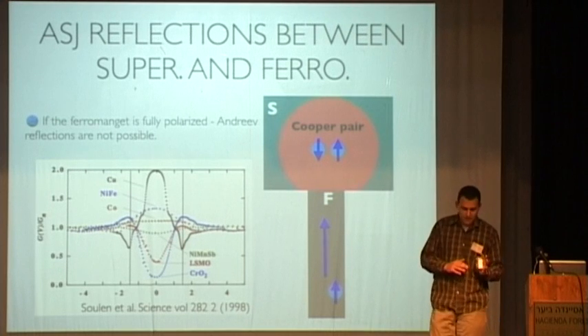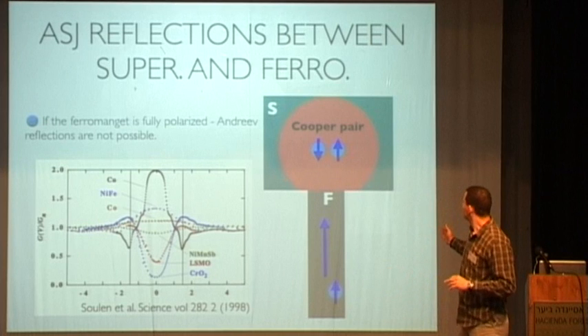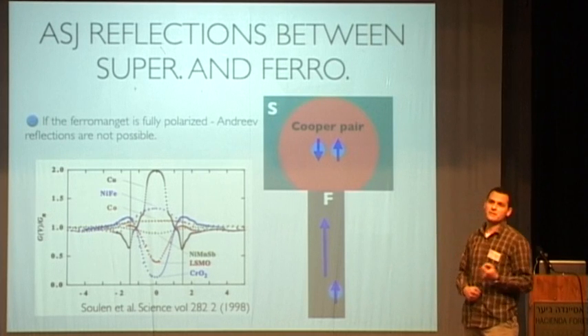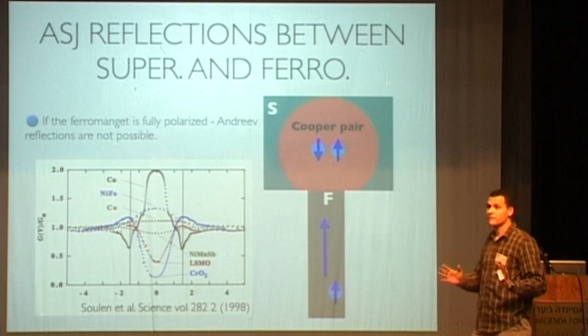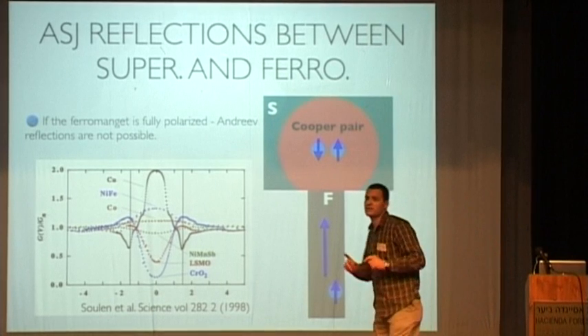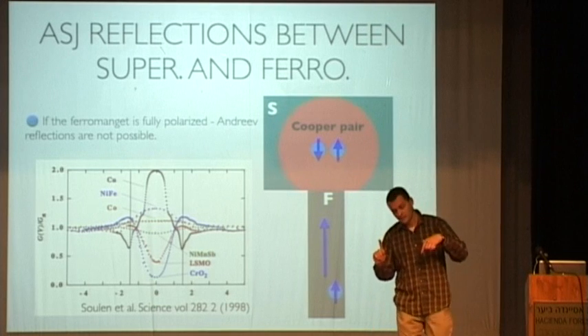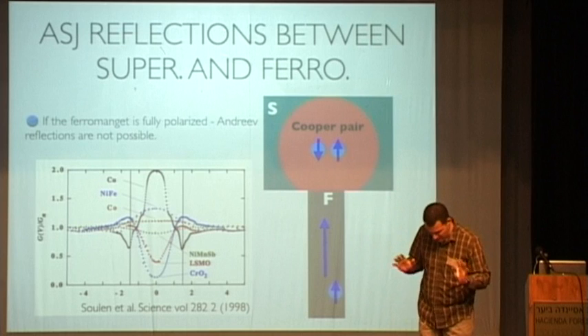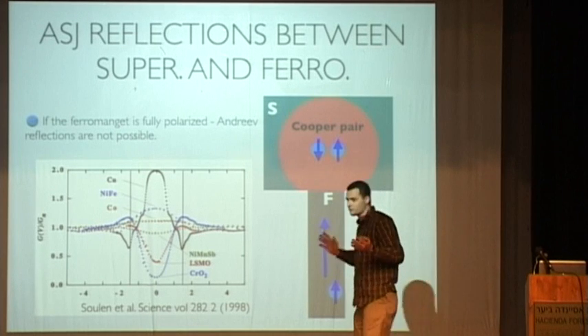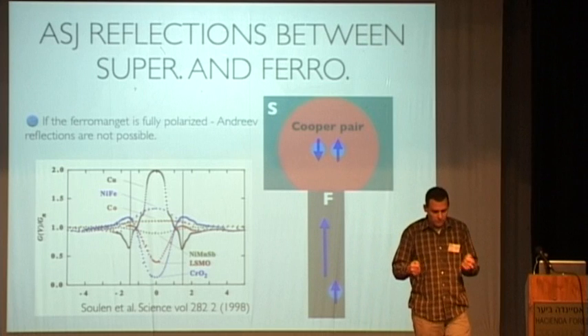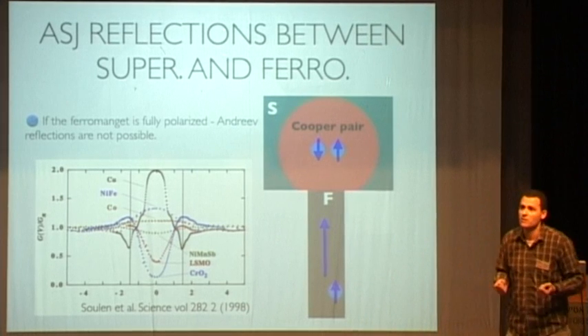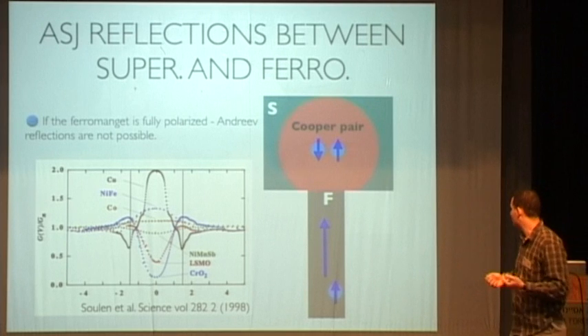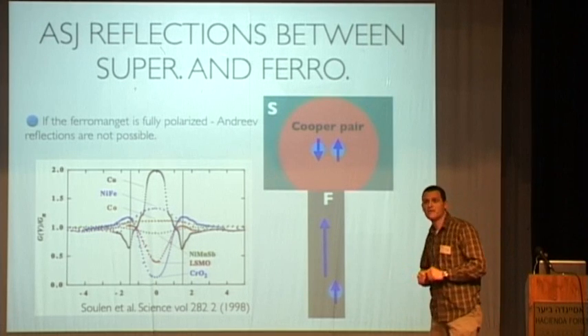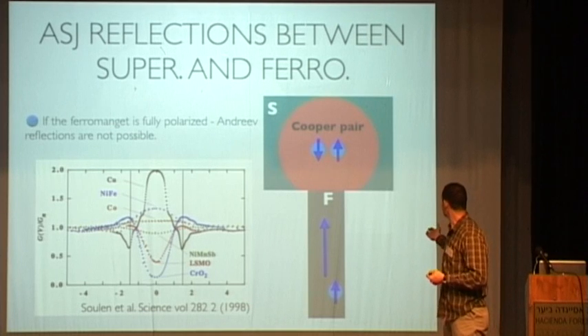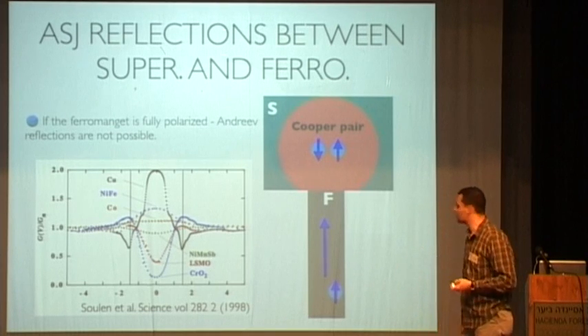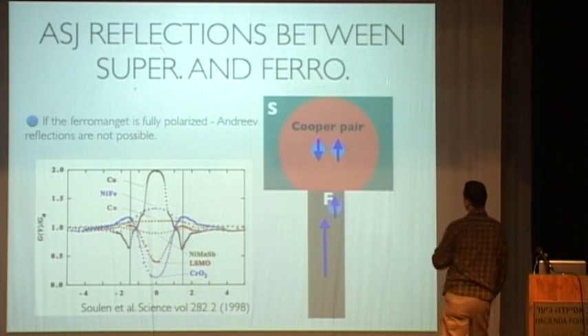If, on the other hand, you look at a ferromagnetic metal in touch with a superconductor, if this ferromagnet is fully polarized, and assuming for now that the spins of the electrons in this pair have to be opposite, which is reasonable to assume at first, because you know that the Pauli exclusion principle doesn't want the two electrons having the same spins in the same place. So they would prefer to have opposite spins. They have the least energy. So let's assume that they have opposite spins. Then for a ferromagnetic metal, if it is fully polarized, this mechanism cannot happen. So the electron will be reflected.